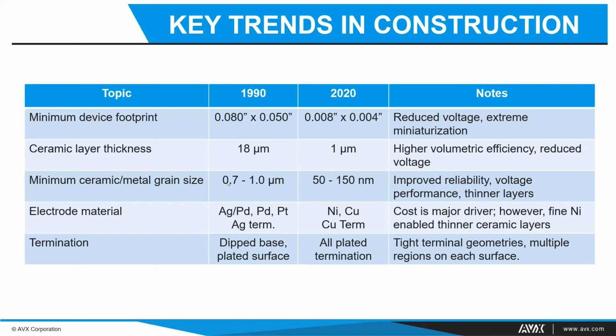The minimum ceramic grain sizes in those days was someplace near 1 micron, but today a more common dimension is something in the nanoparticle range, 50 to 150 nanometers. And this has allowed improved reliability and important voltage performance, and has allowed thinner layers, which has again pushed the volumetric efficiency of the devices. Electrode materials have gone from the precious metal combinations that I described before down to base metal materials, and cost is the major driver in those cases.